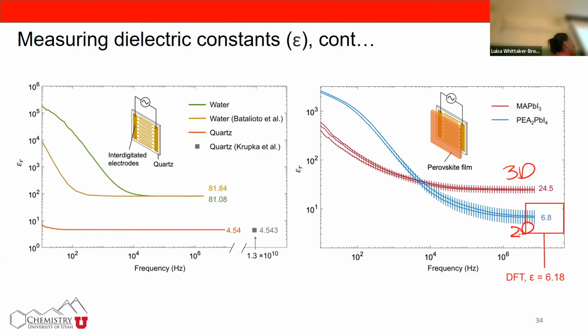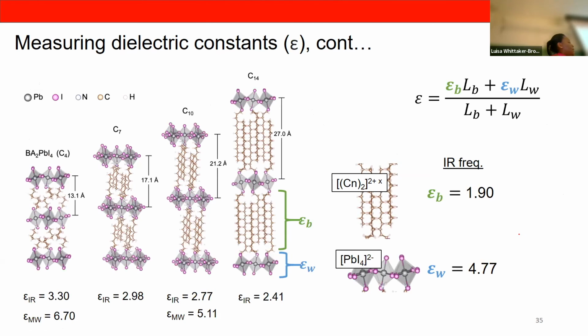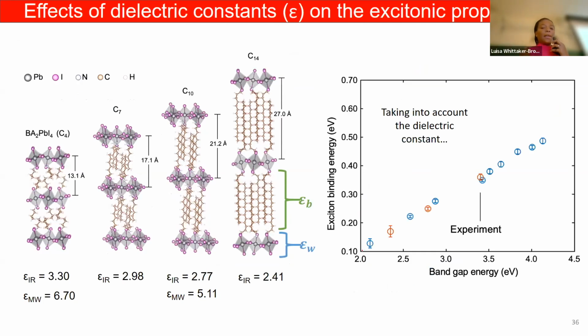So we want the dielectric constant for each of the different layers, right? So we use this formula right here to get what the dielectric constant is for the organic component and the inorganic component. And then when we did that, and we plotted the binding energy as a function of band gap, you will notice that all of them follow the line, okay? So now the issue is that we had to use the same dielectric constant for all the different compounds. So we actually had to measure the dielectric constant for each of the compounds that we were doing in our study, okay?